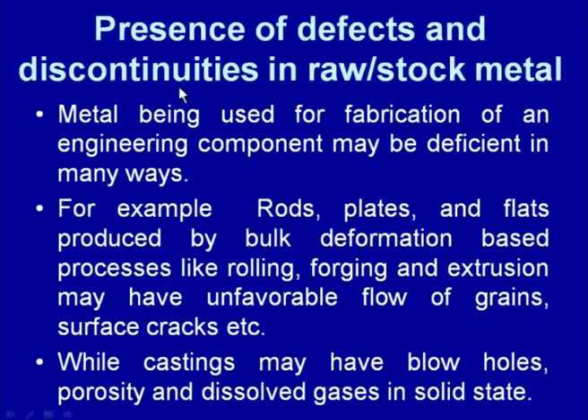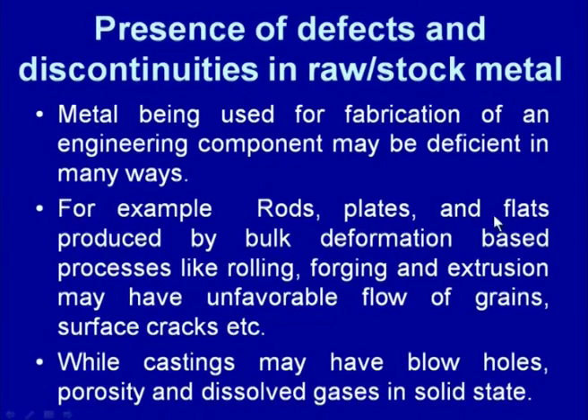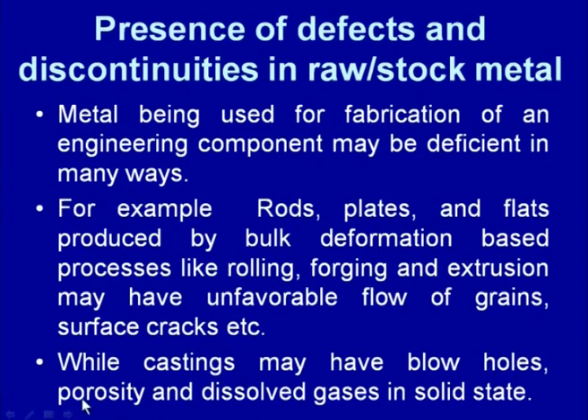Then the presence of the defects and discontinuities in the raw stocks. We know that the raw material in form of the sheets, rods and the ingots is developed using a variety of processes, and these rods, plates, flats produced by the bulk deformation processes by rolling, forging, extrusion, etc., many times have unfavorable features in form of the undesirable grain flow direction, surface cracks, inclusions, lamellas, etc., and in case of castings these discontinuities are present in form of blowhole, porosity, dissolved gases. If these components are used as raw material with the discontinuities for developing other engineering components which can be subjected to the mechanical loads and other service conditions during the service, then the presence of these discontinuities in the raw material and the stock itself can lead to the premature failure of the engineering component.